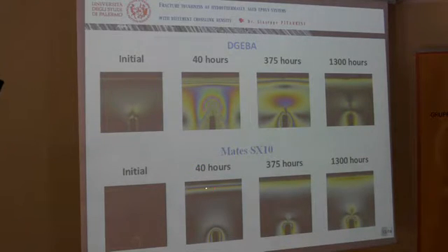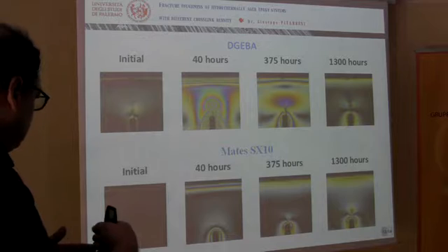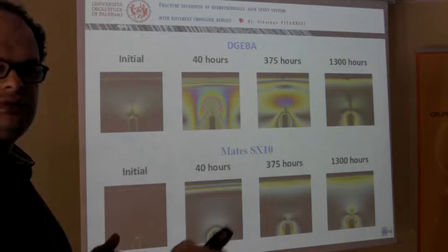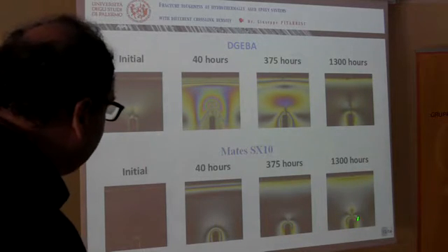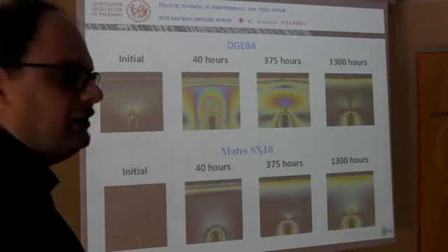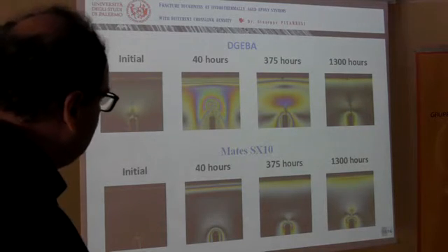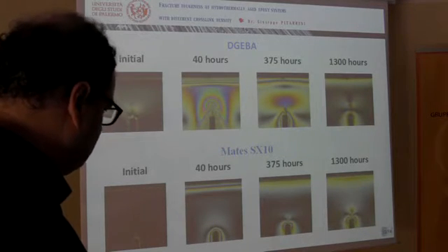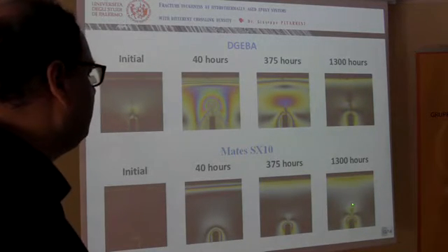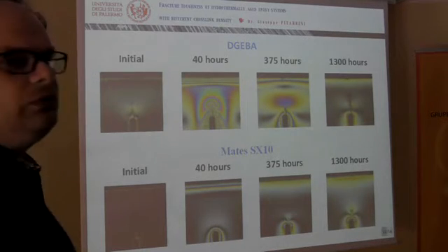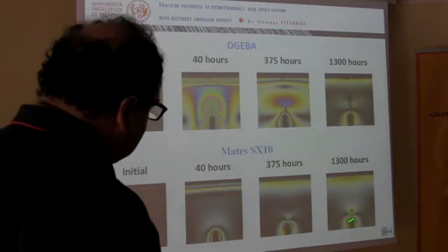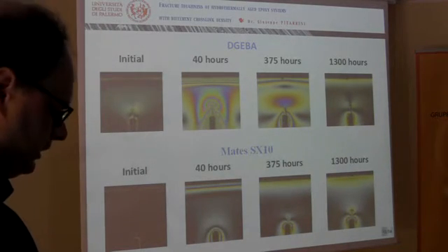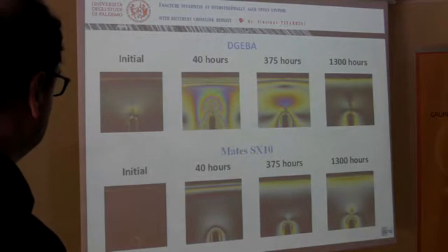As the water enters further into the material and evolves towards saturation, we start to see something rising at the crack tip. And we explain this behavior by thinking that water starts to penetrate the crack and start to penetrate the material through the crack tip. And the stress that is generated here is basically compression stresses. But we will see this in a few slides.